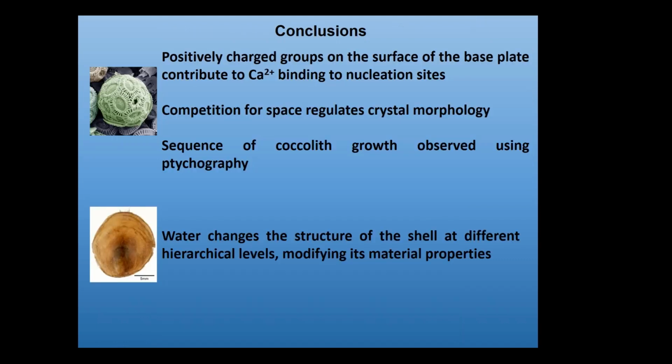So with this, I'm going to finish. To conclude on coccoliths, I showed that there are positive charges on the surface of the base plate that contribute to binding of calcium to nucleation sites, together with polysaccharides. We see how competition for space by crystals growing in a crowded environment is contributing to regulating the morphology of the crystals.